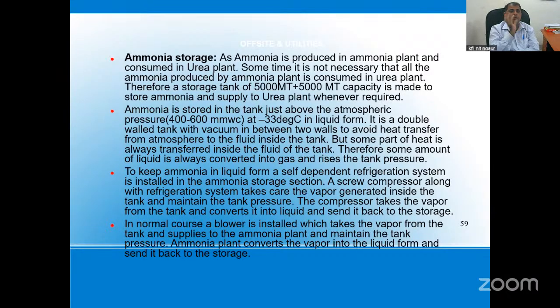Ammonia storage tank is not a simple tank, because ammonia is very dangerous. It vaporizes at minus 32 degrees Celsius, and our storage temperature is minus 33 degrees Celsius. We store all the ammonia inside the tank at minus 33 degrees Celsius, because if the temperature increases and gets to minus 32 degrees Celsius, all the ammonia will vaporize here.